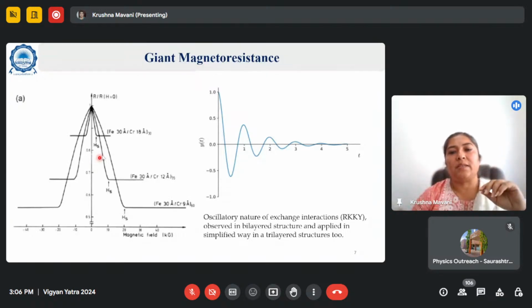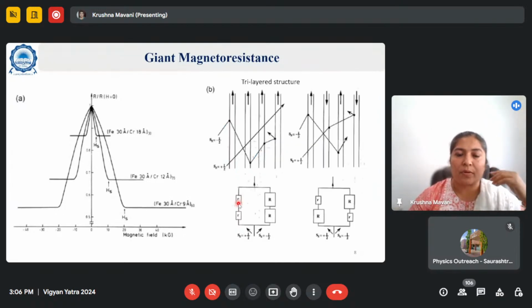If you vary the distance, I have shown one oscillatory function here. This one is time dependent, but assume that this is x actually. This is the distance on the x-axis. As you vary the distance from one spin to another, it is ferromagnetic exchange interaction here. As you vary distance, it goes to anti-ferromagnetic exchange, then ferro, then again anti-ferro, and the magnitude is decreasing. So this is harvested for observation of giant magneto-resistance.